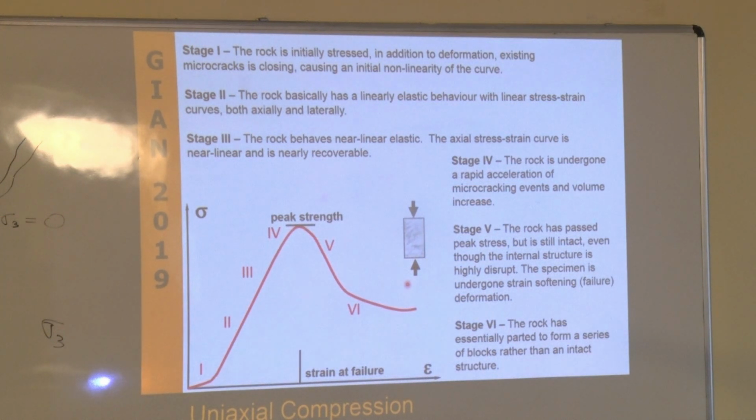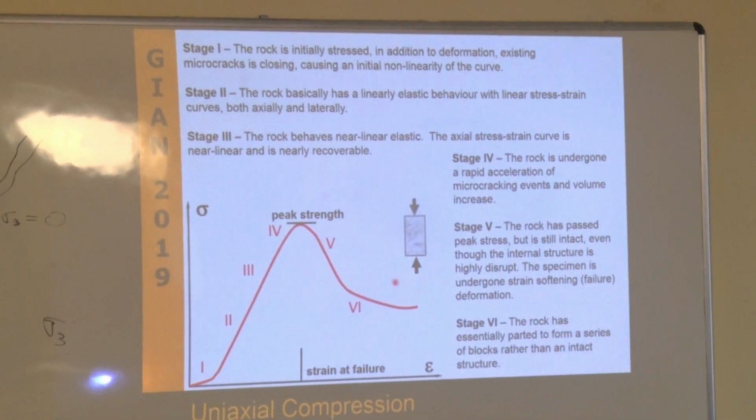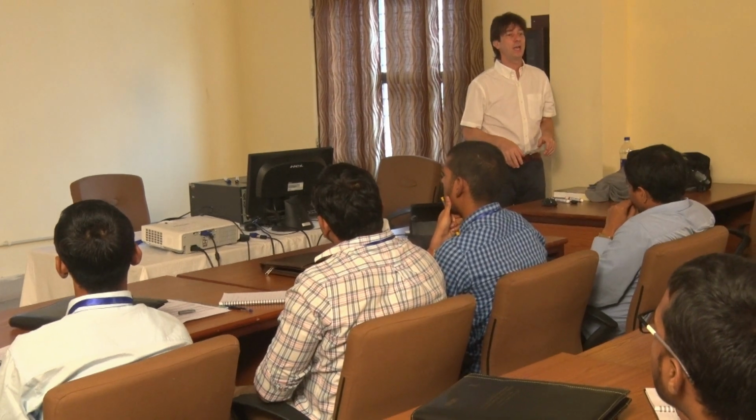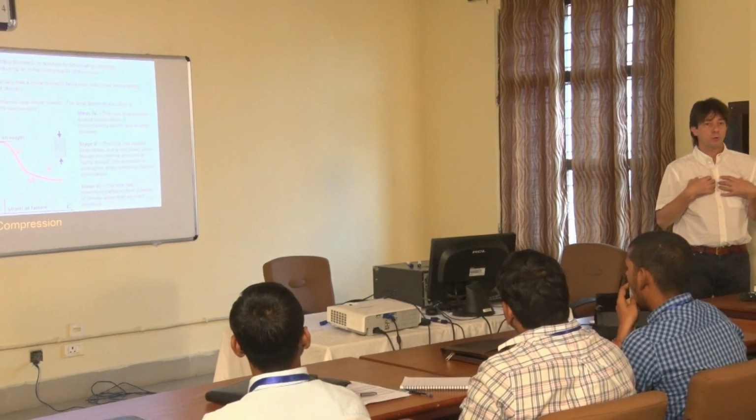Where you always have sort of a shallow slope at the beginning, and generally that is where you have micro cracks and closes, so the material seems softer than what it should be. Plus, the sample preparation, the machine compliance. There's a lot of other stuff that goes into that initial number one curve, that path, that personally, you should completely disregard in 99% of the tests. That is my personal opinion.